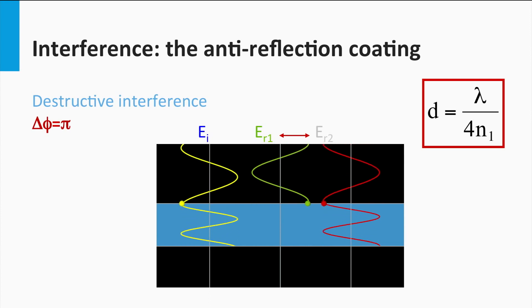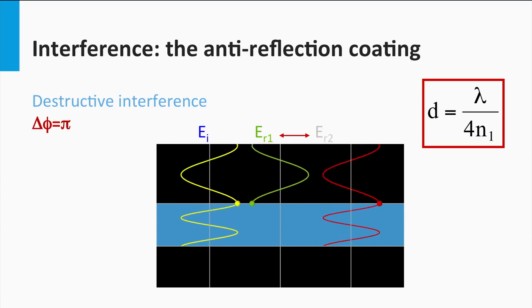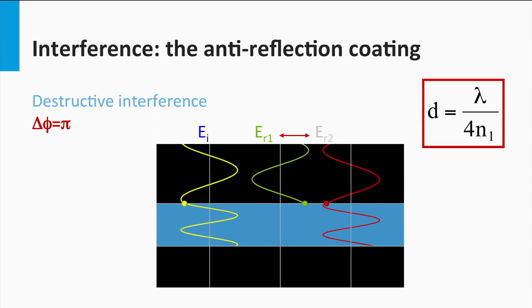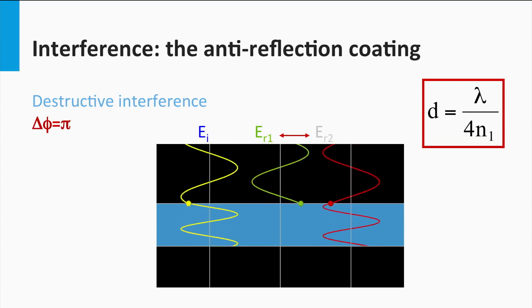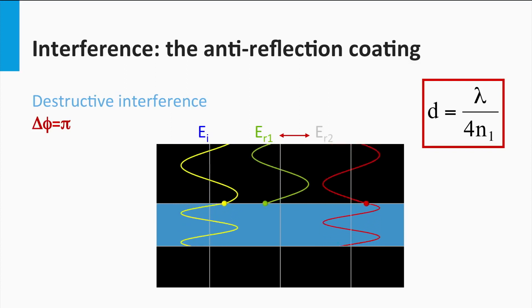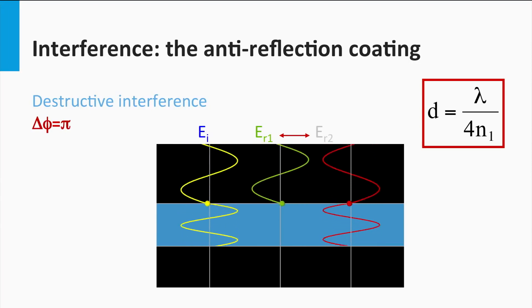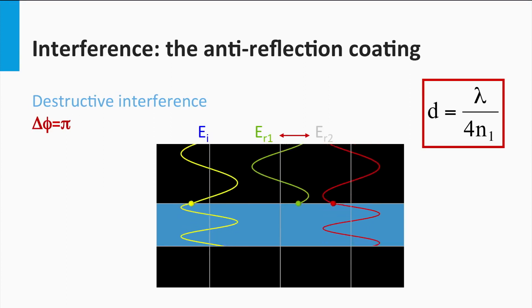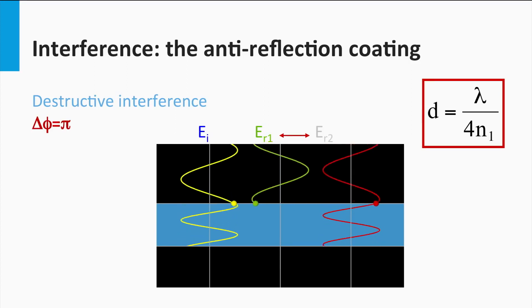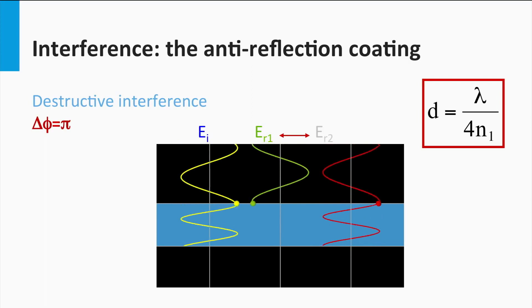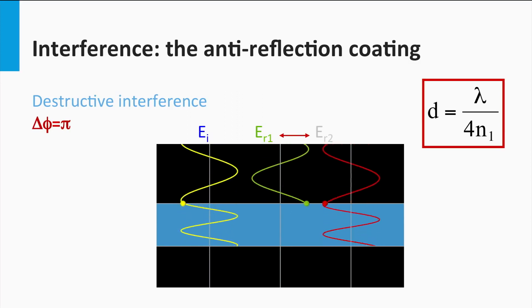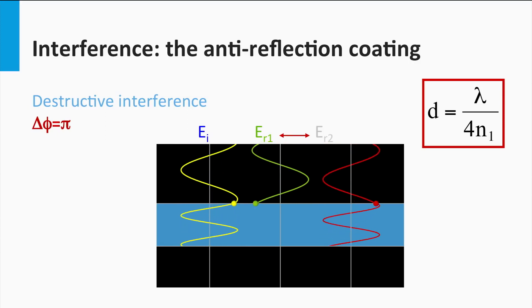One can design an anti-reflection coating based on this principle. We have placed an interlayer between two media. The green wave shows the reflection back from the first interface and the red wave shows the wave reflected back from the second interface. The two outgoing waves appear to be in antiphase, so the total amplitude of the electric field of the outgoing wave is smaller, and the total irradiance coupled out of the system is smaller as well. The maximum destructive interference occurs when the product of the refractive index and thickness of the interlayer equals the wavelength divided by four — in other words, the thickness is the wavelength divided by four times the refractive index of the coating. Using such an anti-reflection coating means the interlayer thickness must be on the order of the wavelength.